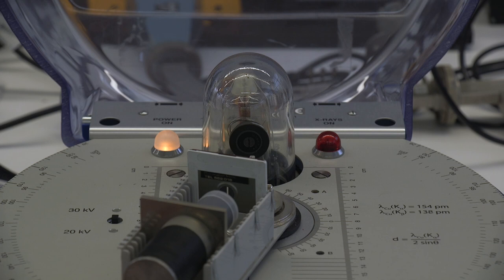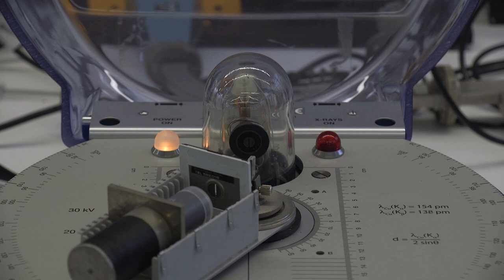I can move the position of this detector and I'll show you in a minute how we measure the angle. In the experiment you're going to do measurements at two degree angle increments to start with. You start with quite a wide coarse spread and then once you have a rough idea of where the diffraction peaks are, the peaks in intensity, you go back and do finer measurements around those angles to determine the exact location of the peaks.